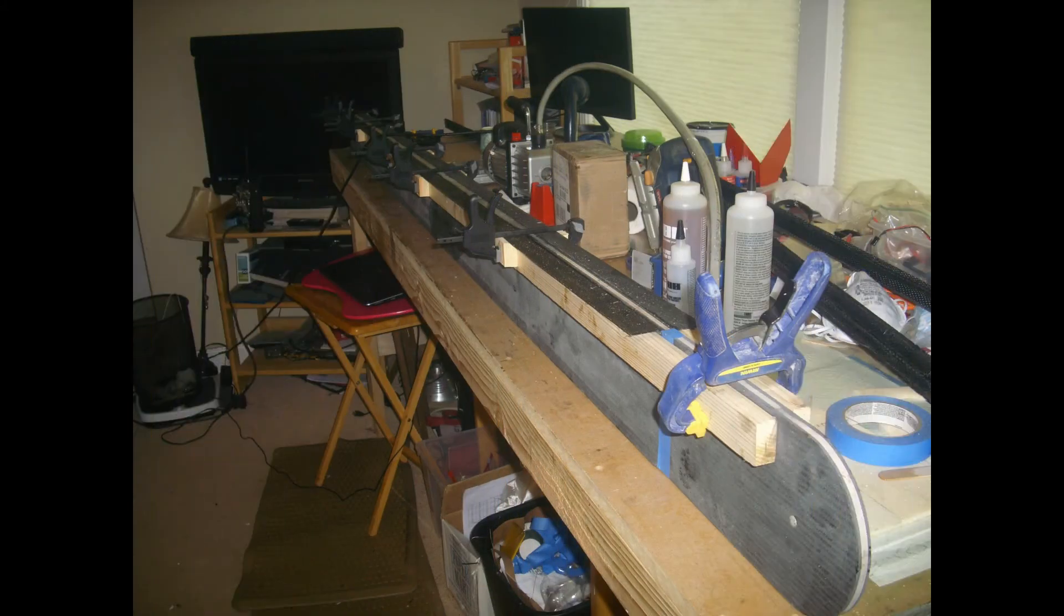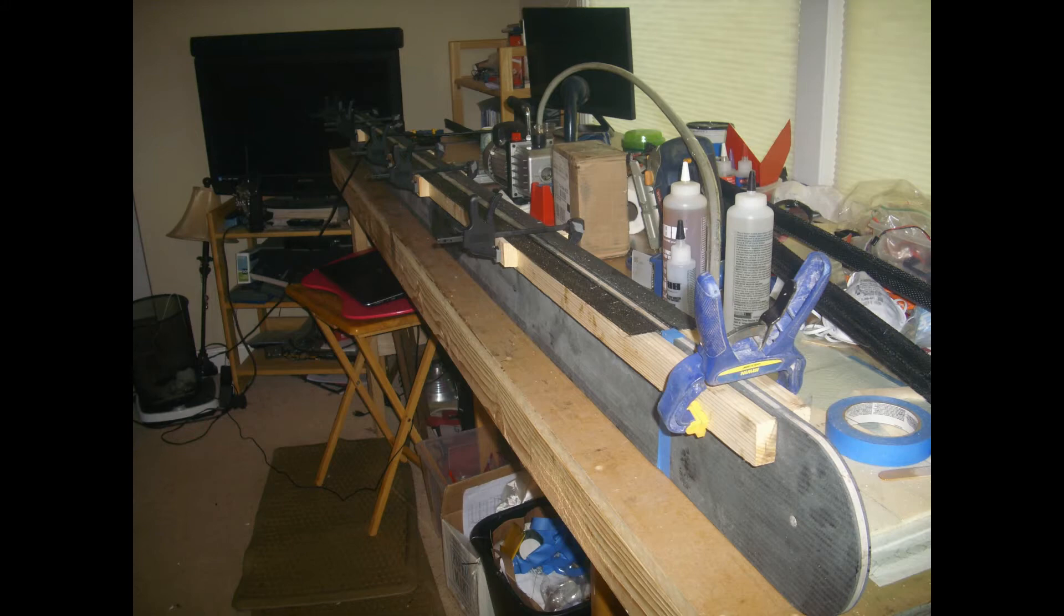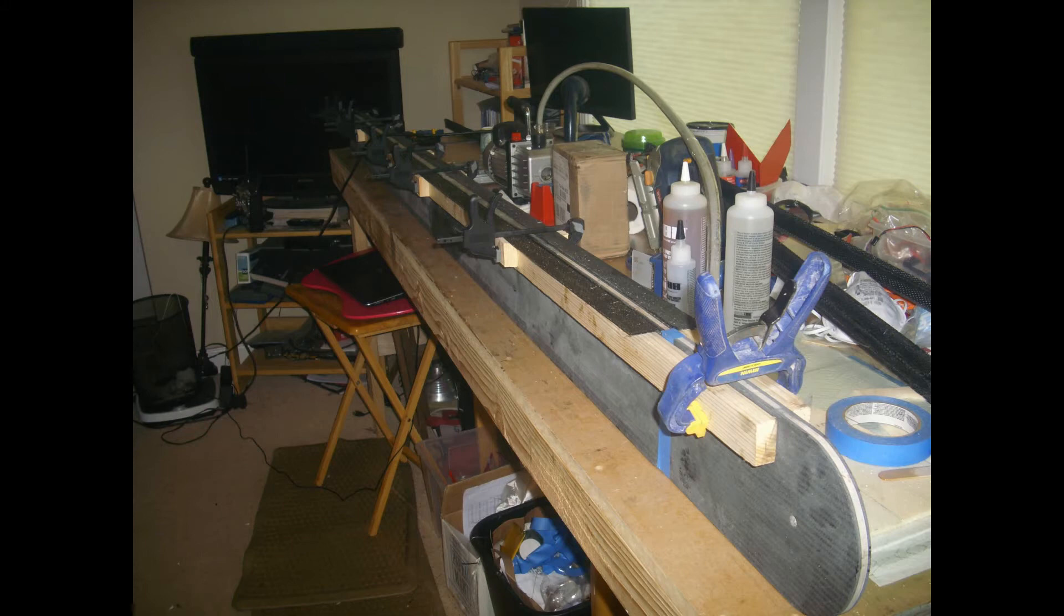In this photo, we see the flanges being bonded to the shear web. I applied a thin layer of T88 adhesive to both the flange and the shear web. I used painter's tape on the shear web to ensure epoxy is applied only where needed. Given that 50% of the weight of composite aircraft structures is adhesives, it is important to use only just as much as needed to bond the parts. I used a couple of 1x2s and clamps to hold the flanges in place while the epoxy cured. I applied these flanges in two steps.